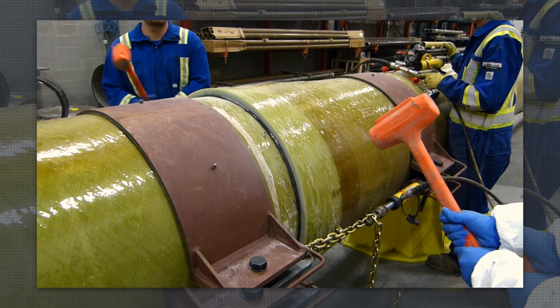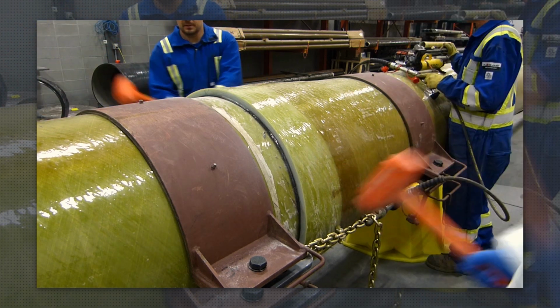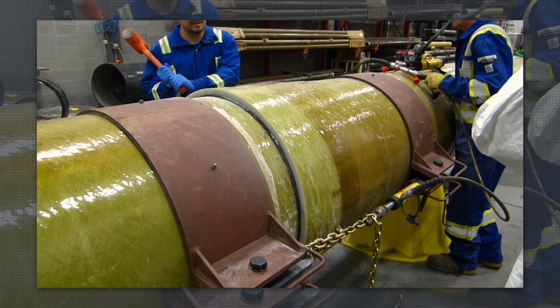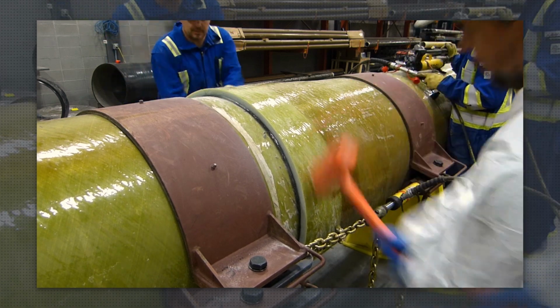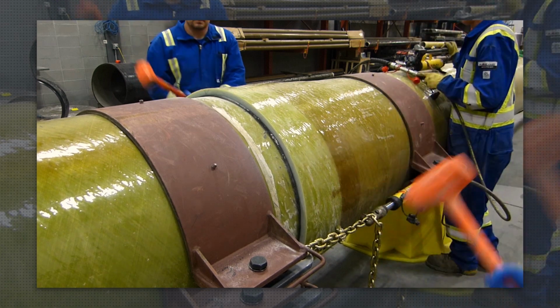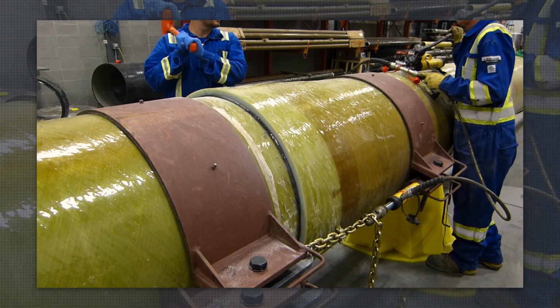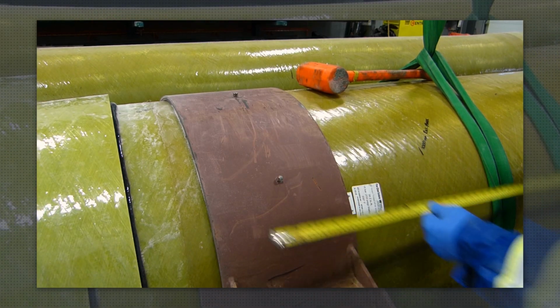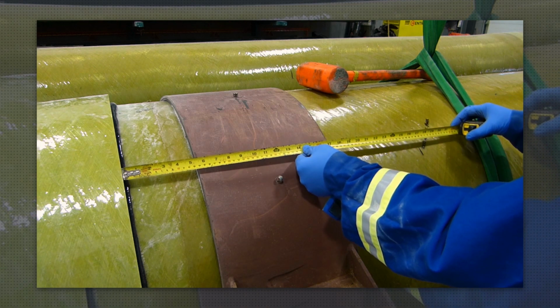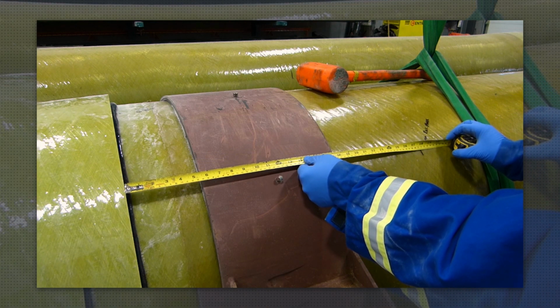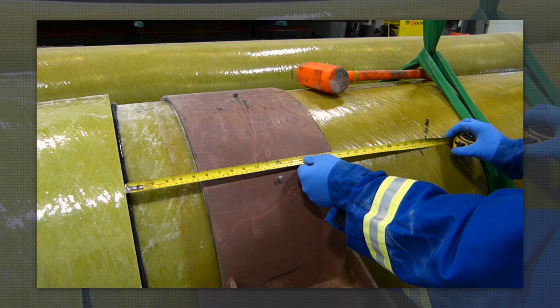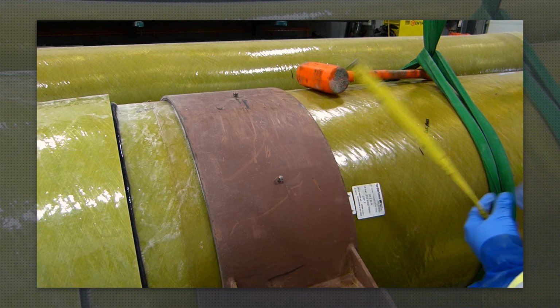Hydraulic pressure drop is monitored after successive hits with the dead blow hammers. When pressure drop is 200 psi or less after 3 consecutive hits with the dead blow hammers, the joint is locked up. The installers measure from the face of the bell to the reference lines added to the spigot end to check final insertion depth and verify that it is within specification.